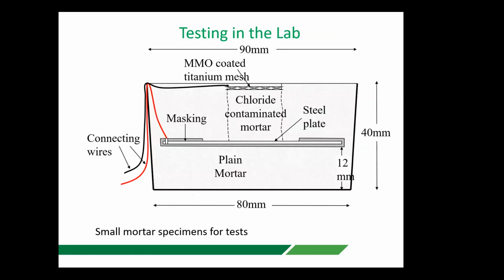So we tried that out in the lab. We made some small specimens, little mortar specimens where we had a steel plate which was masked all around apart from a central ring. And we introduced chloride contaminated mortar in the center of that, away from the edges so that we could avoid crevice corrosion. And we then applied, using a small MMO coated titanium mesh anode, a cathodic current density to the steel reinforcement.